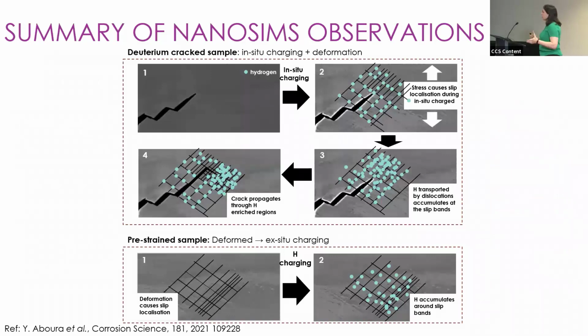So just to summarize what we saw from those nickel alloys, if we look at our in situ charged sample while it was being cracked, we have our crack growing in here. As we do our in situ charging, from the stress, we get these dislocation slip bands around the crack, and we get the hydrogen segregating to those regions. The hydrogen then starts being transported around by those dislocations, and it accumulates more strongly at those dislocation slip bands. And then the sample will crack further as it cracks into a region of hydrogen or deuterium enrichment.